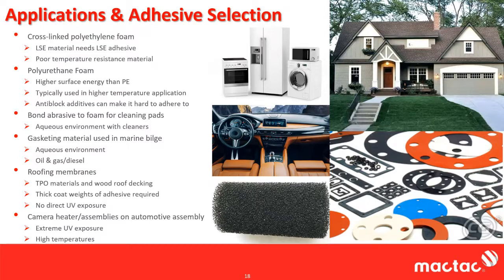cameras sit up behind the rearview mirror at the very top, so they get defrosted or defogged last. So what everyone's starting to do with their cameras is put printed circuits that are heaters around the camera, and so the camera has its own dedicated defroster that's always running. Well, in this case, because it's on a windshield, which is glass, there is extreme UV exposure. So we would never ever recommend a rubber-based adhesive for this. It wouldn't last more than 6 months. Also, there are very high temperatures here, not because of the interior of the car, but because that printed circuit can get up to several hundred degrees to keep that area around the camera defrosted and de-iced.